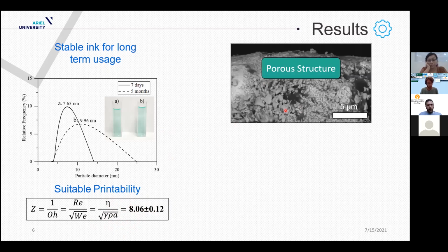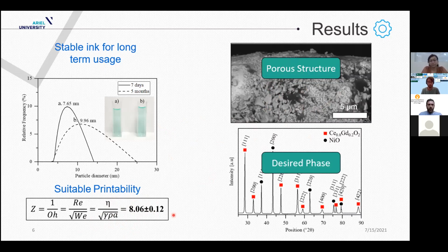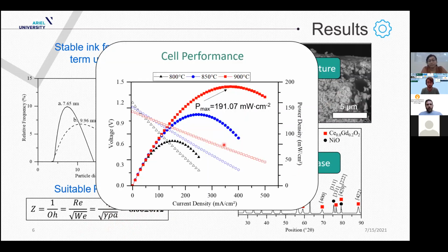The printed anode had a desired porous microstructure, as I said before, and the desired phase of nickel oxide and gadolinium doped ceria. By testing the anode performance in a fuel cell, it shows that there is potential for further development in terms of the maximum power density that we get.